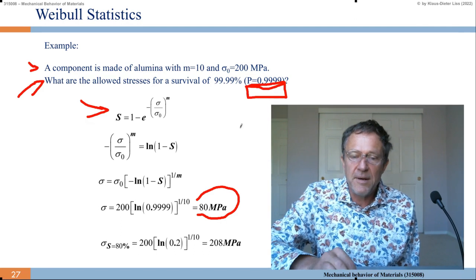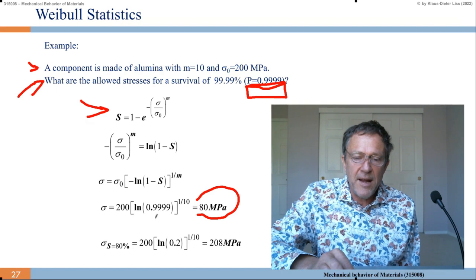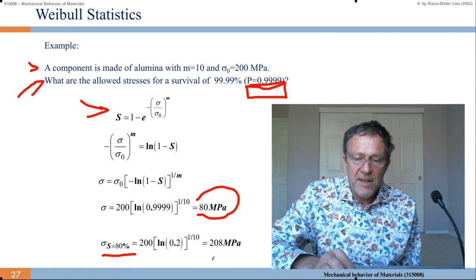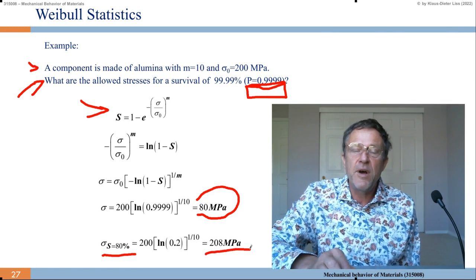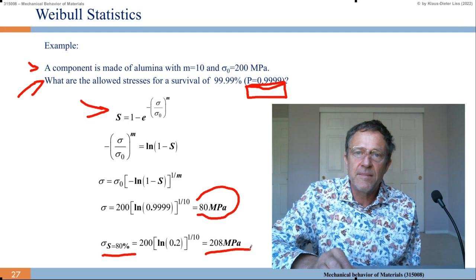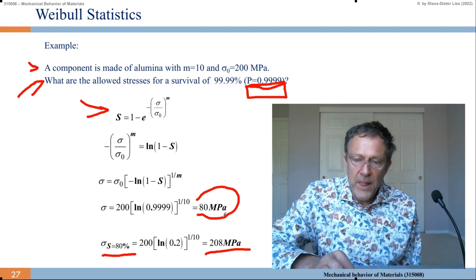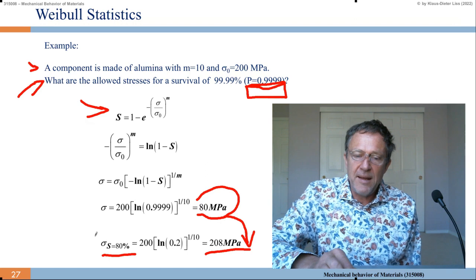As an example, what happens if I put 80%, not 0.9999, but 0.80? So for S is 0.80, then it works out to 208 megapascal. We see we can increase the stress, but then the probability of survival for 80% goes down.